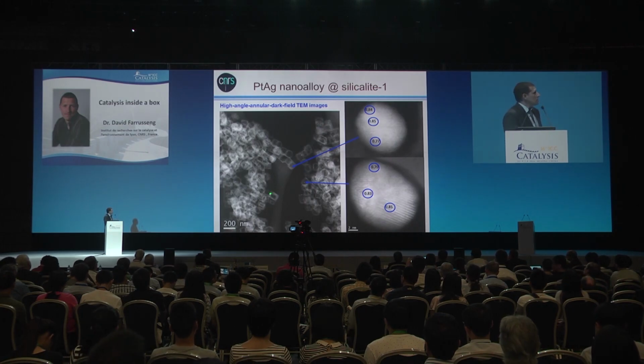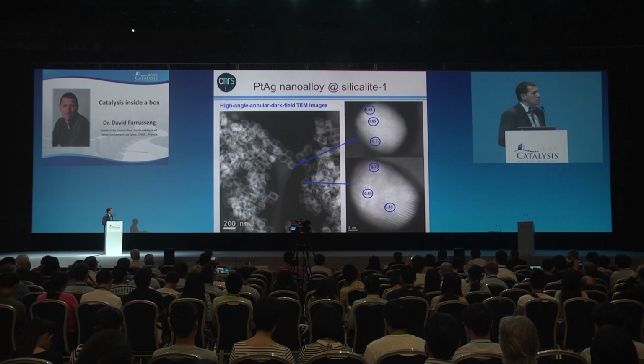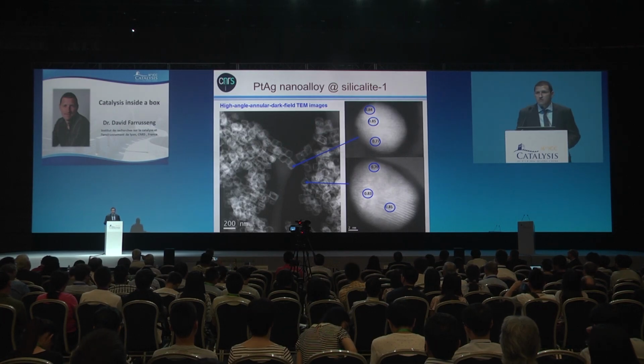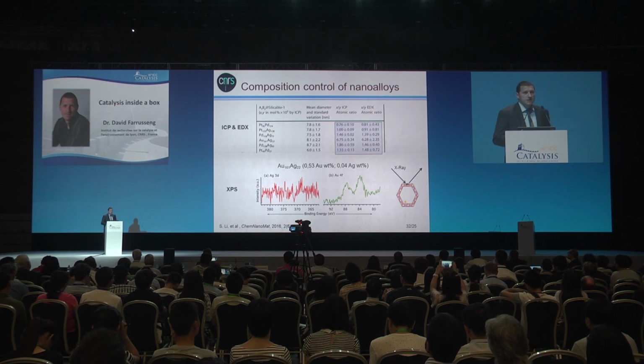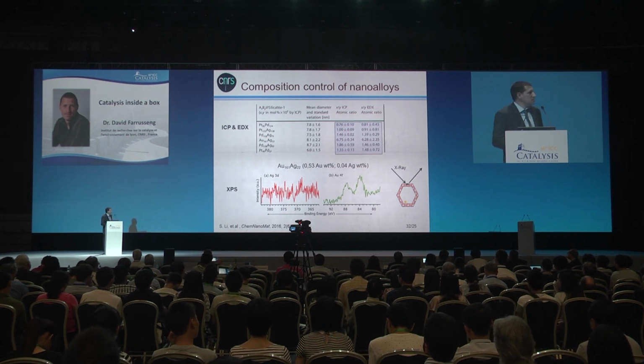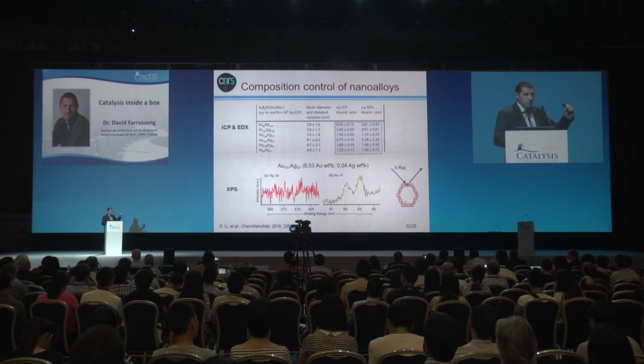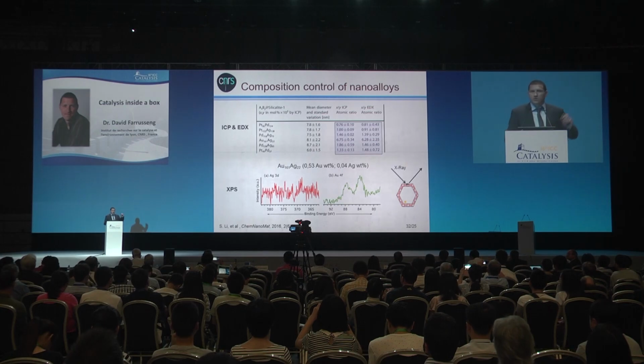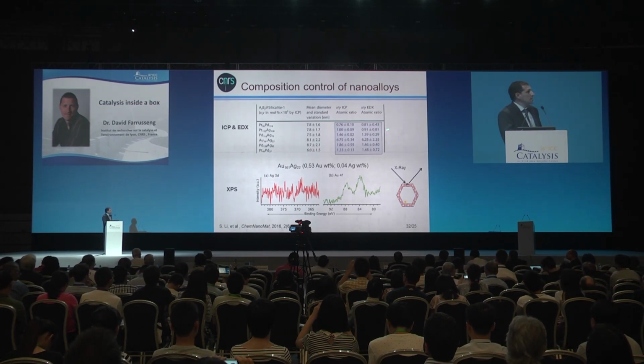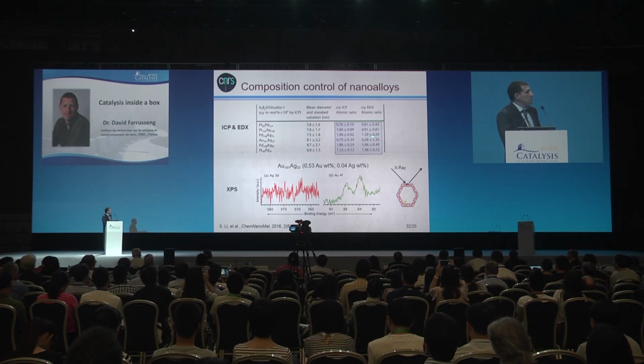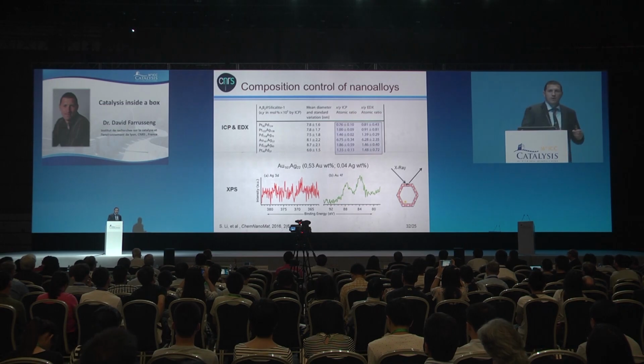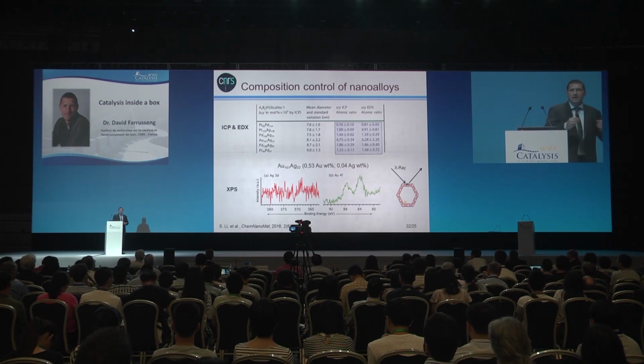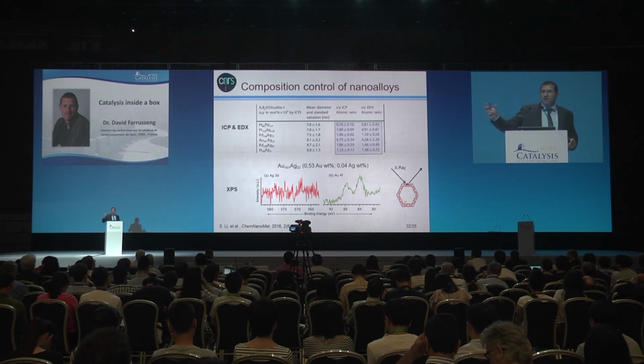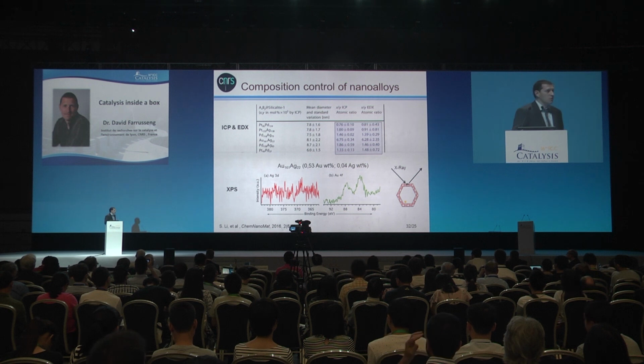So every white spot here is a particle, and we look at different spots on these particles to look at, for example, the Pt or silver ratio. You can see that on one particle it is very homogeneous. And we repeat that for all the bimetallic systems we did. So we have done EDX analysis on about 20 to 30 different nanoparticles and made an average and statistics here. And you can see that they match pretty much with the ICP analysis here. It means that every particle is composed of both elements, that we don't have silver here and platinum there. They are all mixed together in a very homogeneous composition.